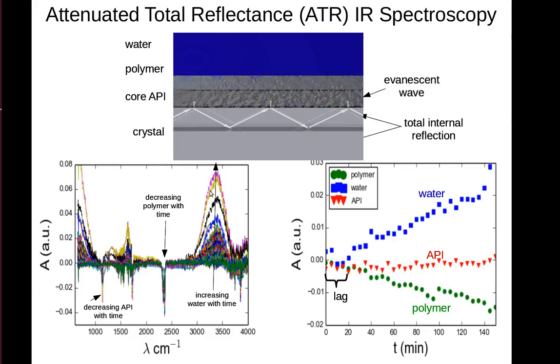This can be quantified and viewed a little bit easier if we plot the absorption at specific slices in our spectrum bands as a function of time. You see at the beginning of the experiment there's a lag as the water has to penetrate through the material and get to the crystal surface. After that initial lag, we start to see the water intensity growing in. We see the polymer being dissolved. And for this particular polymer experiment, we see that there's very little change in the API signal, suggesting that the API is not leaving the vicinity of the evanescent wave.